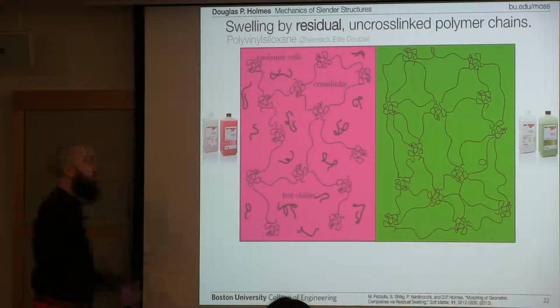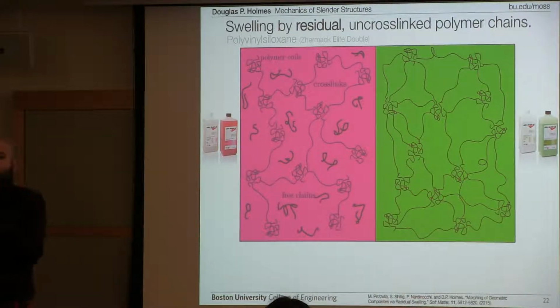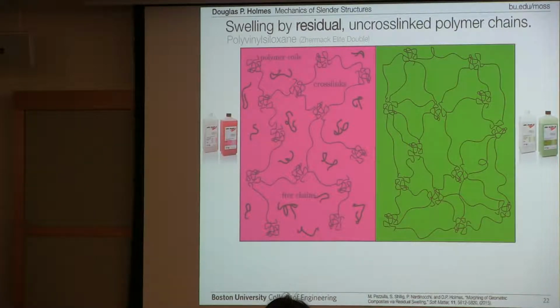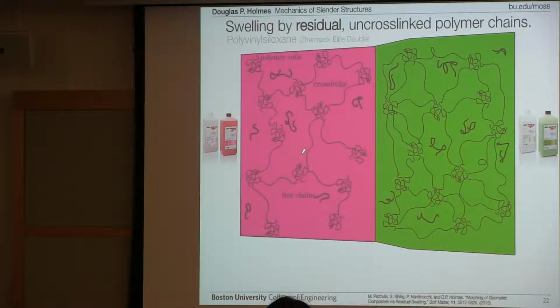These things here. If you put these two things together, it's like sticking a dry sponge to a wet sponge. You stick a dry sponge to a wet sponge, fluid from the wet sponge will migrate into the dry sponge. It'll cause the pink part to shrink. It'll cause the green part to get bigger. And this is residual swelling, because you're swelling the structure with residual material that's left in this pink polymer here.